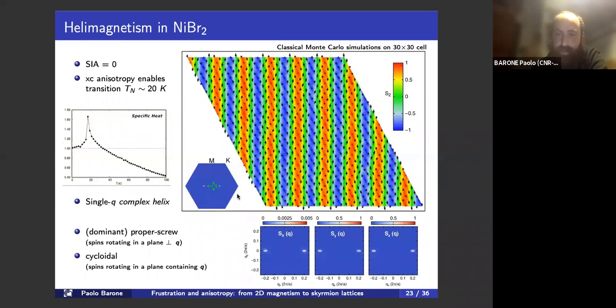And what I've shown here is a snapshot of the spin texture at low temperature taken from the Monte Carlo simulations. And the color scale is the component perpendicular to the plane. And what you see from here, it looks like a proper screw, where the spiral modulation is parallel to the x direction, and the spins rotate in the plane perpendicular to it.